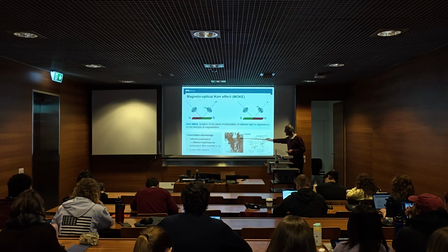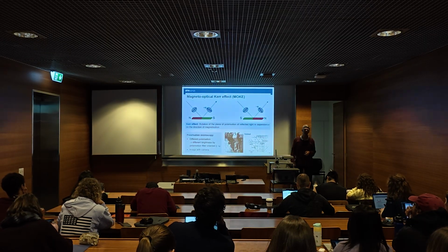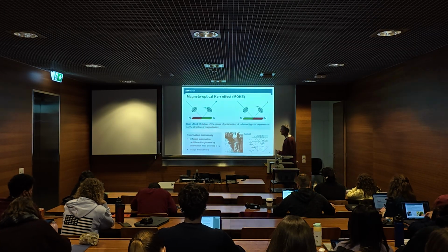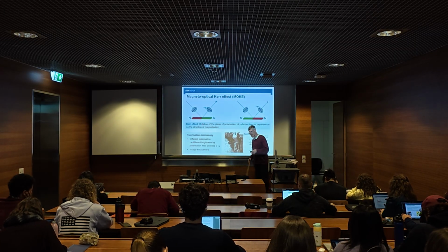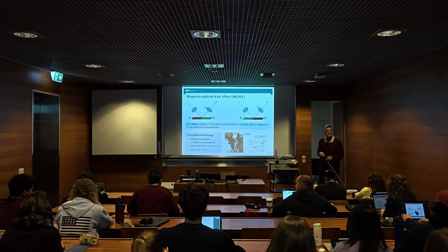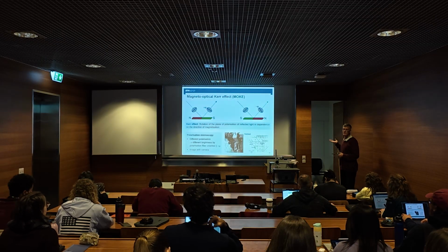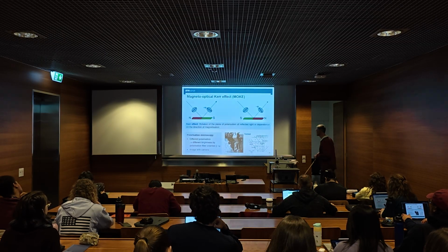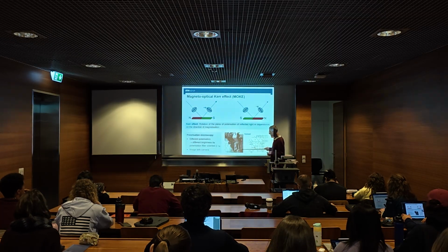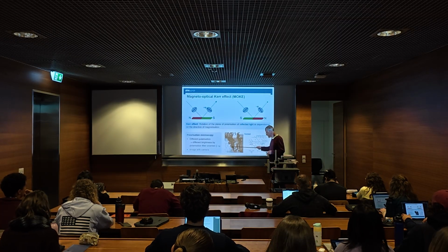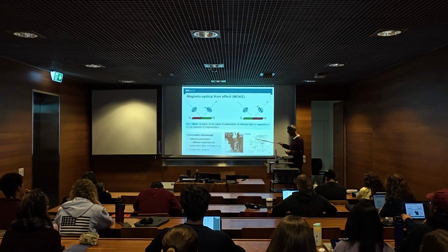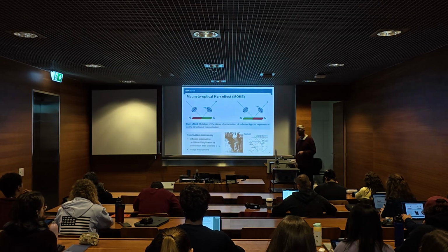So you can nicely image plus and minus magnetized regions on the sample with that. Very convenient. Again, 1 micrometer resolution. You just need the light source and then a polarizer in the microscope, and then you see your domain distributions magnetically. Very nice, very convenient. Here you see nickel. This picture you have also seen before, and then how the different brightness from this polarization microscopy experiment converts into magnetization directions is shown here.